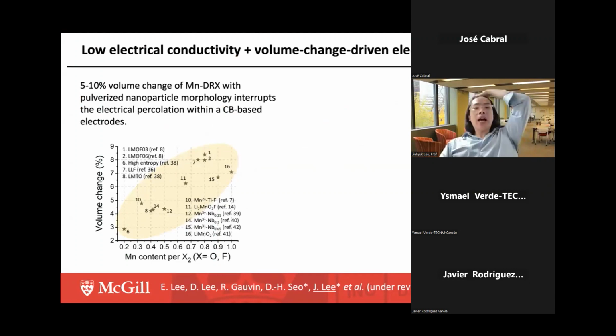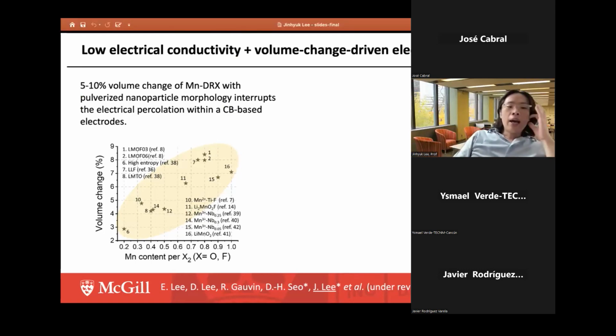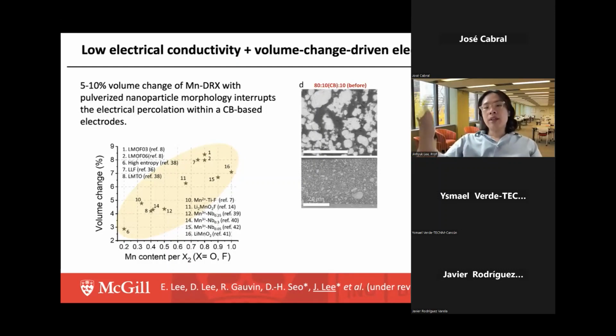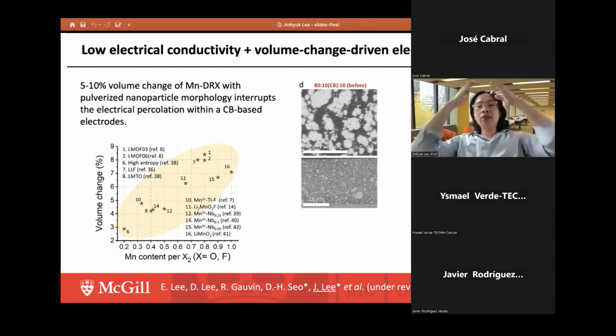And what we also found is that, besides this low electric conductivity, the manganese DRX materials typically exhibit a 5 to 10% volume change during charging and discharging. And with the pulverized nanoparticle morphology, what happens is that during charging and discharging, the electrode starts to disintegrate. So for example, here I'm looking at the cross-section SEM image of this 80-10-10 electrode material. And here the white part is the DRX material, and the gray part is the carbon black.